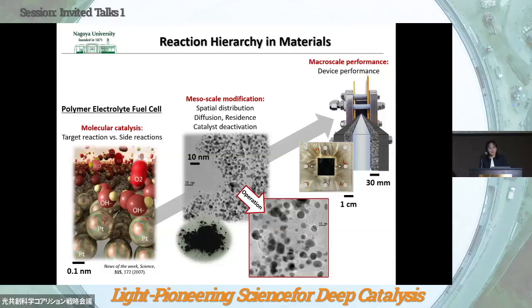There are many events in a practical cell, for example, diffusion and residence of the reactants and products, and the degradation of the catalyst and membrane. You can see the typical TEM image of the platinum catalyst, which is a quite fine platinum nanoparticle supported on carbon. Before the use, it was highly dispersed in the cathode catalyst layer. And after the long time operation in a PEFC, you can see the large aggregation formed in the full part of the catalyst layer. So the degradation occurs in the mesoscale. But tracking this event is still quite challenging.